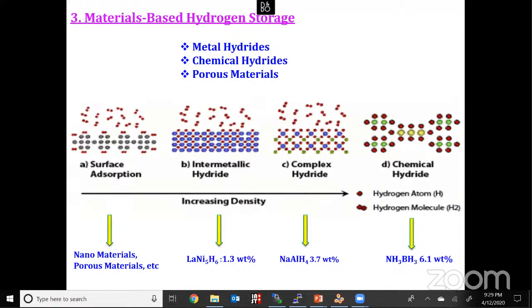Here, I have highlighted a few materials: metal hydrides, chemical hydrides, and porous materials. Today I'm going to talk mostly about porous materials. The advantage of using porous material is that the guest molecule, that means the gas molecule, won't chemically bind with the porous material. It will physically bind with it. That means to release the gas molecule, we don't need to give any additional energy. By increasing temperature or reducing pressure, it will release the adsorbed gas molecule.